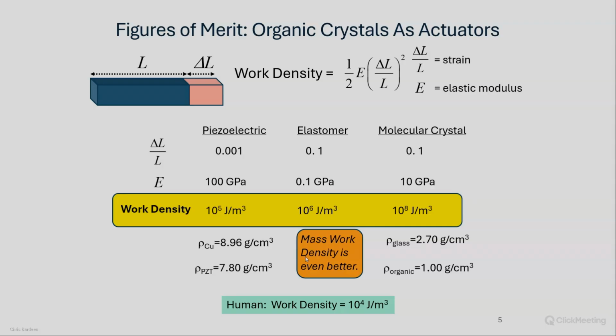So on the top, this is just sort of my engineering slide where I have a rectangular crystal that elongates by an amount delta L. So delta L over L is called the strain. And E is the elastic modulus, which is basically a measure of the hardness of the crystal, to put it in very, very layman's terms. And so the work density, the maximum amount of work that you can expect to get out of this deformation, this expansion, is 1/2 E times the strain squared. So obviously the dependence on strain is stronger.